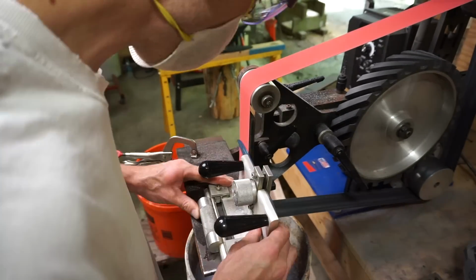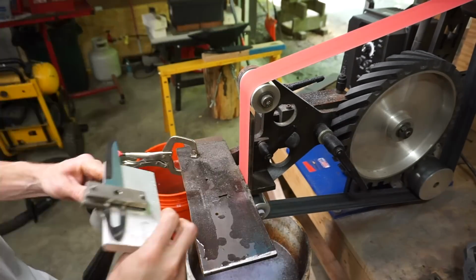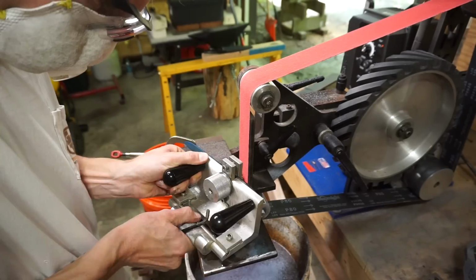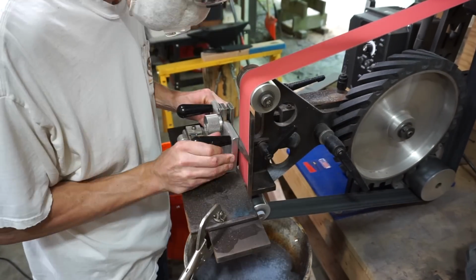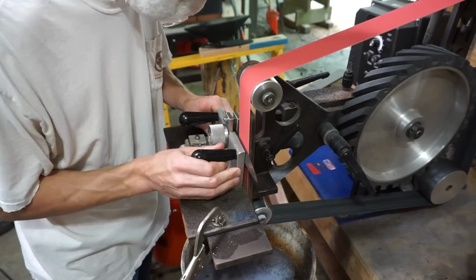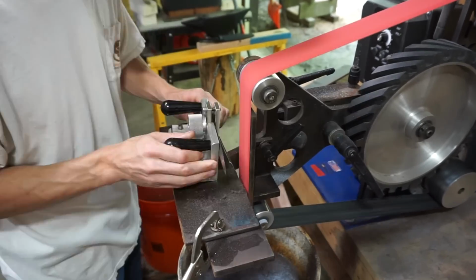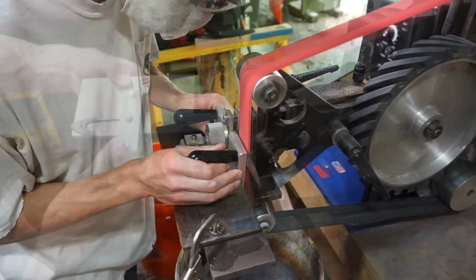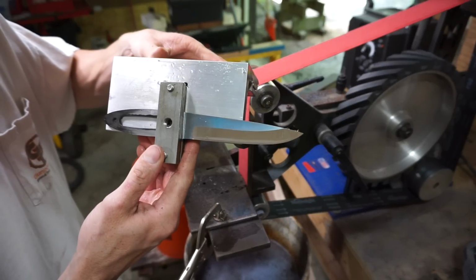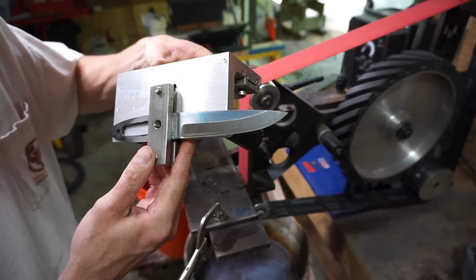So grinding 3V post-heat treatment is a pain in the butt. This took a very, very long time to grind. 3V is no joke. The wear resistance on this steel has to be extremely high, and I can tell that immediately the second I put it on the grinder.